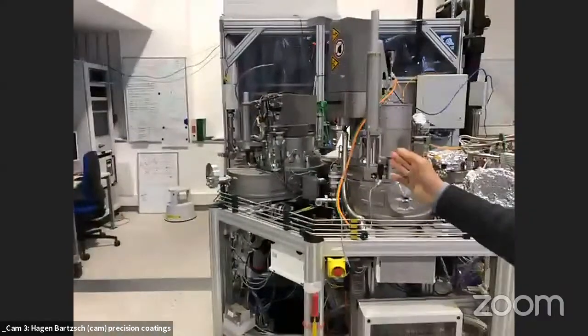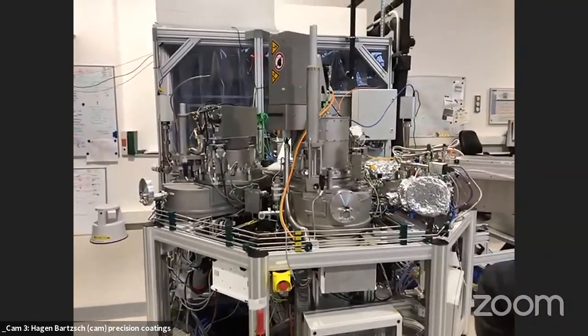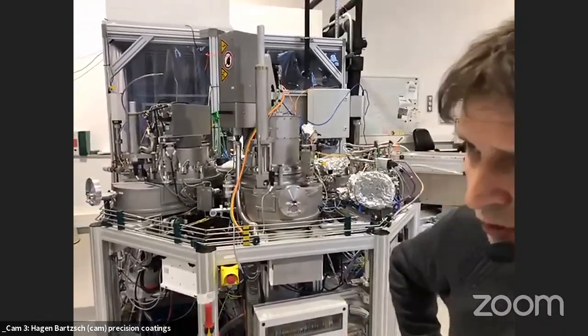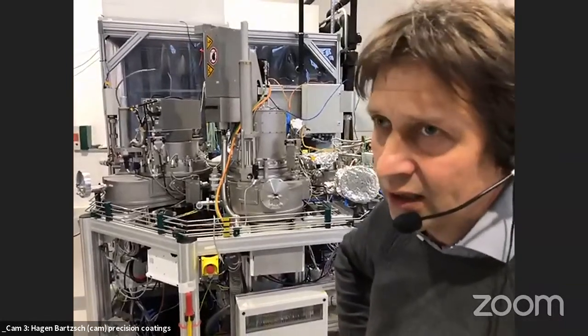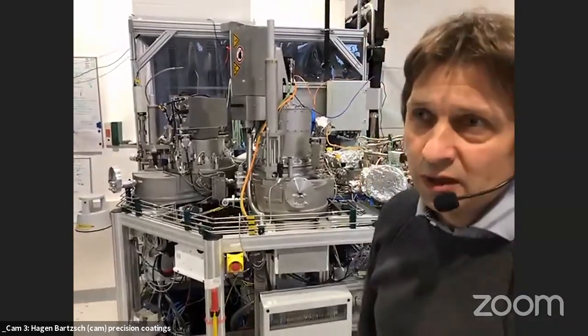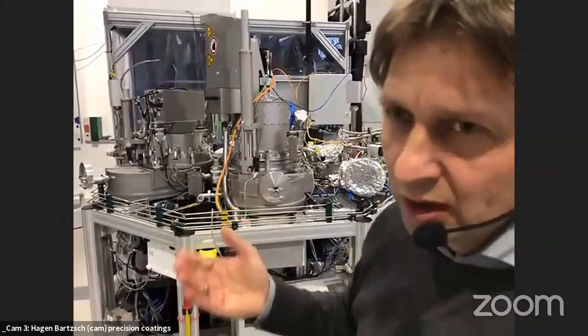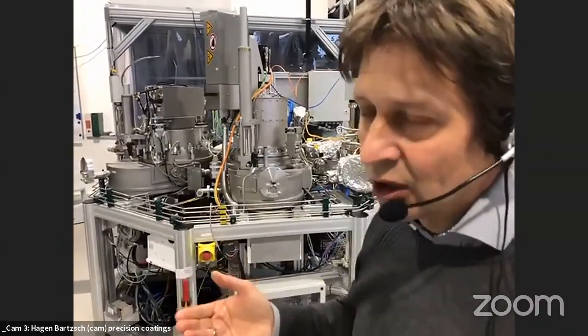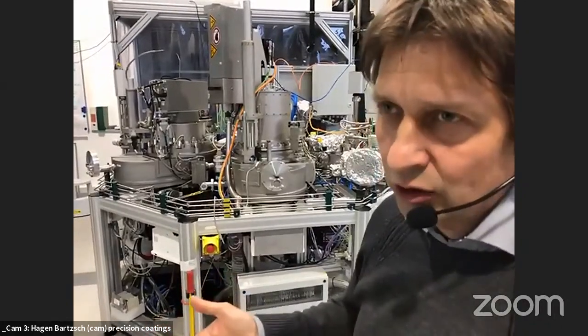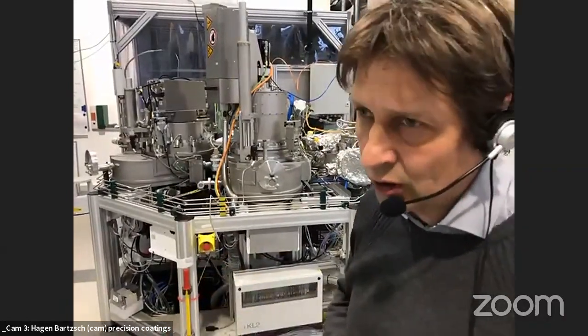The cluster equipment has six magnetron sputtering deposition stations for optical and electronic applications. Currently it is being used for a highly innovative project: sputter epitaxy of aluminum nitride and gallium nitride films for high-power electronic applications — conventionally deposited by MOCVD at extremely high temperatures.